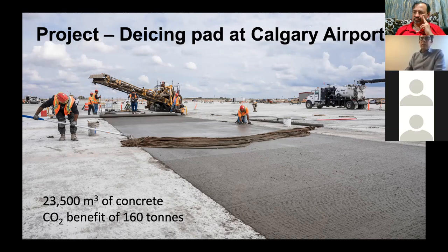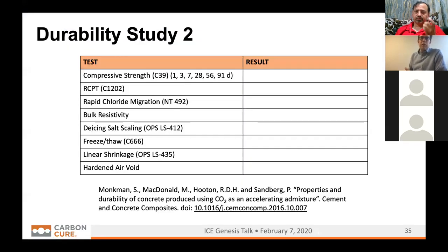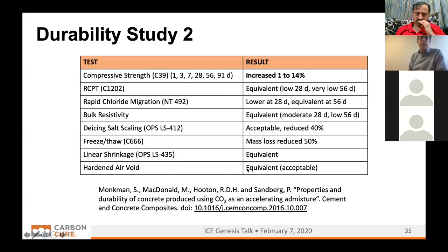And so we found that the CO2 would go in, and you've not changed the void spacing, you've not changed the size of the bubbles. And that was published in a paper, I'll pull up the slide, in 2016. So this paper, if you look at hardened air void, the bottom line, that was where we tried to directly assess the air entrainment.